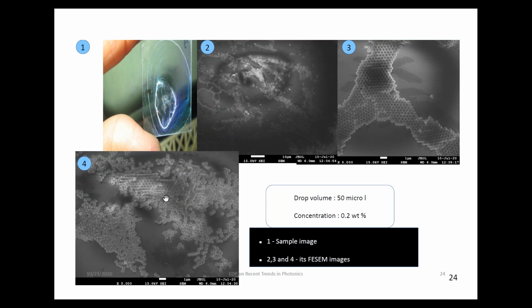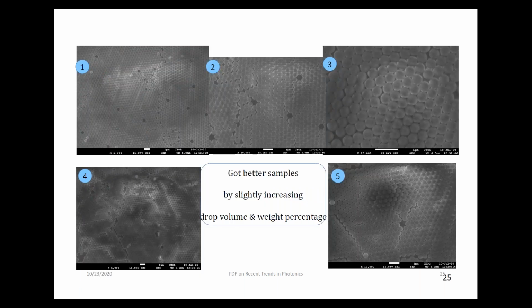So here you see how it looks when you look at the slide, and if you take a SEM image, how it looks. So these are slightly better by adjusting the drop volume and the weight percentage. So you see that there are a lot of defects. You can see there are voids in them, defects in them, and so on. So this is not the best method, I would say, but still it's one of the easiest methods to follow if you want to make a three-dimensional photonic crystal.